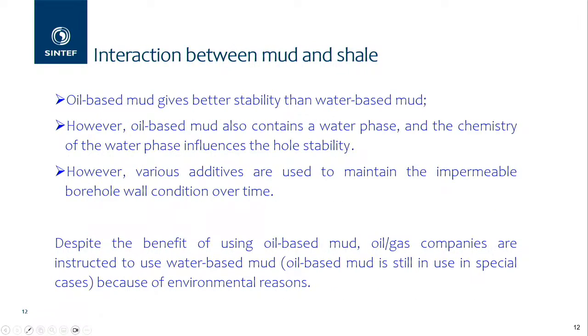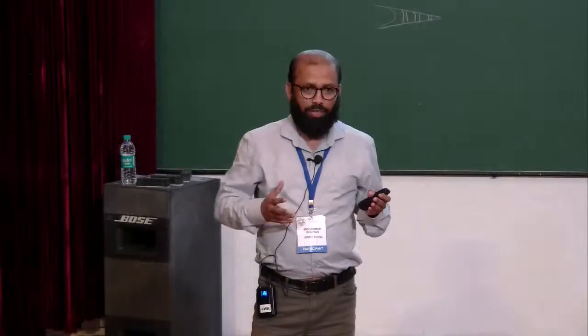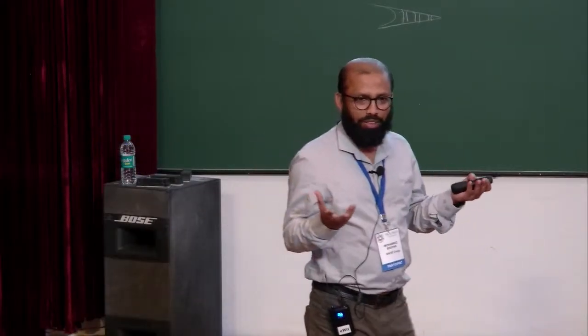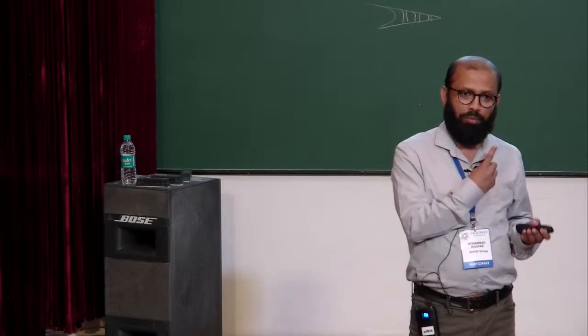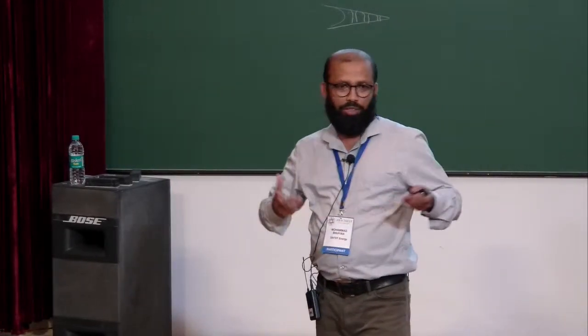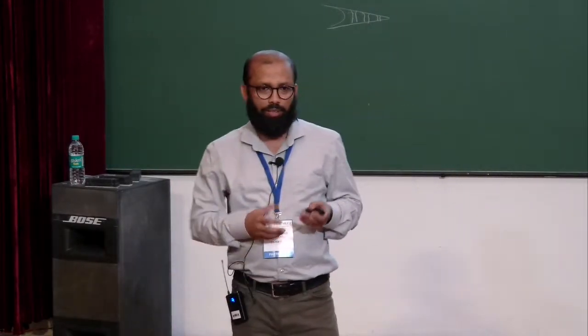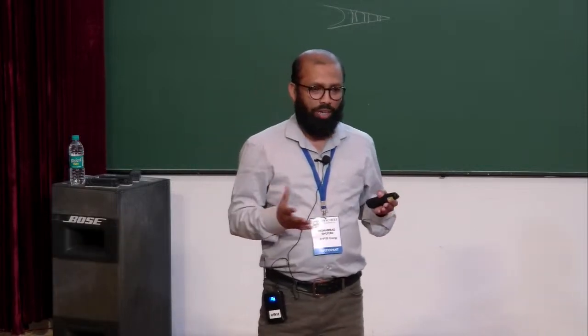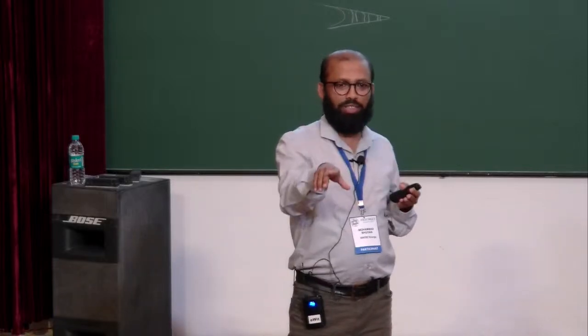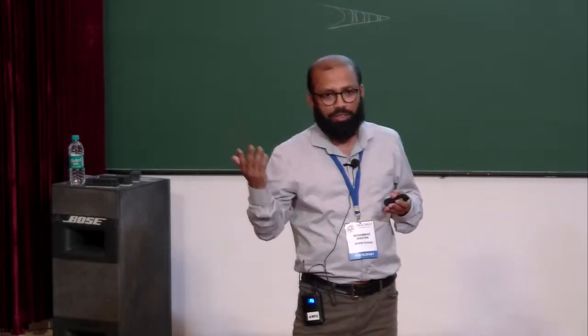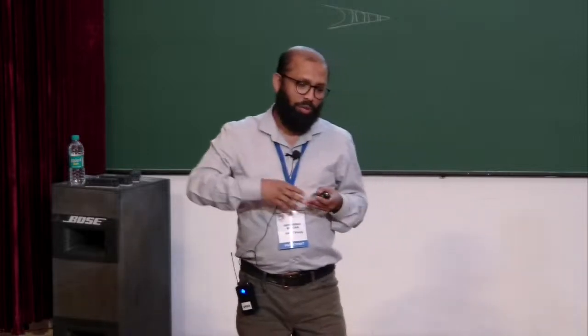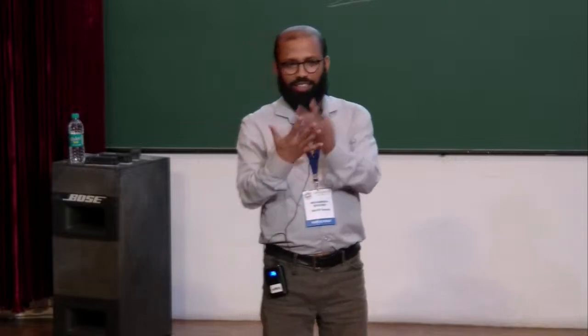Next slide. Yes. Before we became very aware of the environmental issues, we used to deal with water-based and oil-based mud. It's not only that we have oil and we just drill it, because oil-based mud keeps the wall stable. Why? The capillary pressure, because oil has a high capillary pressure to enter into the shale, right? So most of the time it's more than 10 megapascal, it can be more. And to increase the capillary pressure, they also use some gel. It's like a chemical agent that makes a net on the borehole wall, and oil cannot penetrate.